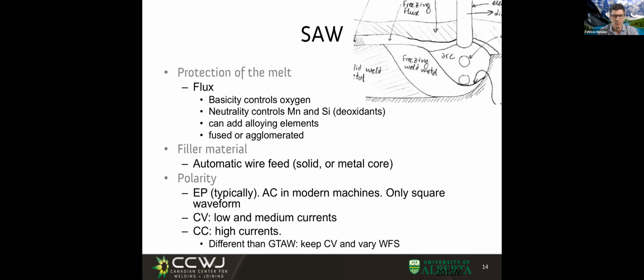The fluxes are extremely interesting because they give us the possibilities of playing games with the weld. For example, we can add alloying elements together with the fluxes. So when the fluxes melt, we are also melting alloying elements, and this way affecting the composition of the weld. That opens possibilities that are not open, for example, in the case of MIG.